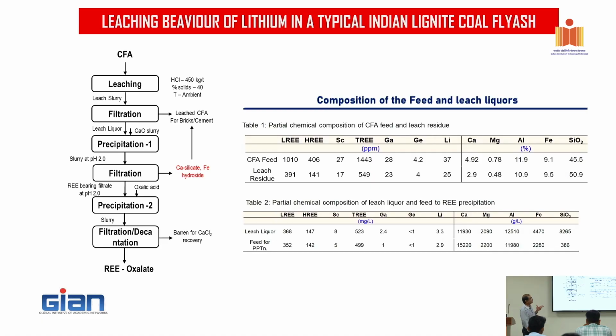Now we tried to do this on some coal fly ash. The ballpark tests have shown that the lithium content in that particular feed is 37 ppm, very low. But once you do the leaching, it has taken only 12 ppm. The residue is still containing 25 ppm. Then we went back to the thermal power plant to ask what their temperature is. They told us 900 degrees centigrade. Then we understood the reason. There are two reasons. One is the concentration itself is not very high. And the second thing is the boiler temperature is also more. Therefore, because of these things, it is not effective.